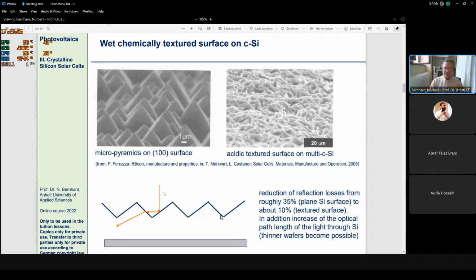That means this texturing has two purposes. First, increase the incident radiation, that means reduce the reflected radiation. And secondly, extend the path length through the crystal. And of course, extending the path length means increasing the probability that finally a photon is absorbed. That means just by texturing the surface, the reflection, which is roughly 35% for a smooth surface, is reduced to about 10% on the textured surface. And this is really quite a big difference. You see, this is a big difference in performance for such a simple measure. And the second one, you see, since the path length is increased, in principle, thinner wafers become possible. And of course, thinner wafers mean we save money because we don't have to purchase so much silicon material.